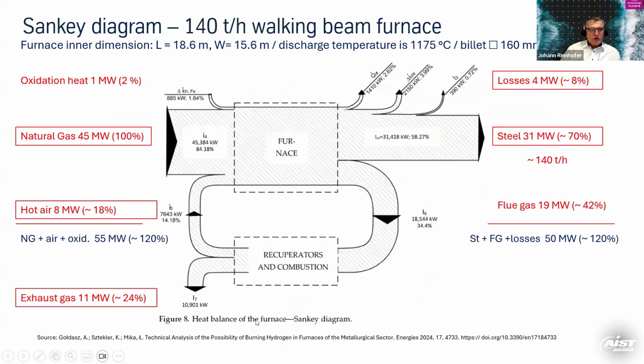Here we have another Sankey diagram of a 140 tons per hour walking beam furnace. The inner dimensions are 18 meters long, 15 meters wide. Discharge temperature is 1175 degrees for square billets, 160 mil, 15 meters long. We don't go into too much detail, but you see again the same pattern. You have the flue gases coming out, and the recuperator, which enables us to preheat the air. Here in this furnace, the hot air supplies approximately 18% of the energy back into the furnace. That's a lot, and this furnace is not even optimized, I would say. So it can be 20, 25, and even more.